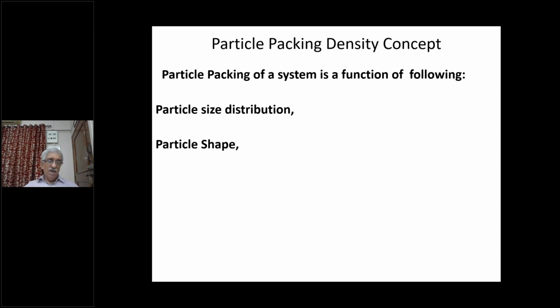Particle shape, fly ash and ultra fine fly ash are superior to, I would not say superior, but they are better and more efficient because their particle shape is spherical and they consume less water. Particle surface, if it is crushed aggregate or crushed ultrafine material, then the particle surface will be rough, whereas if it is spherical, it will be smooth.